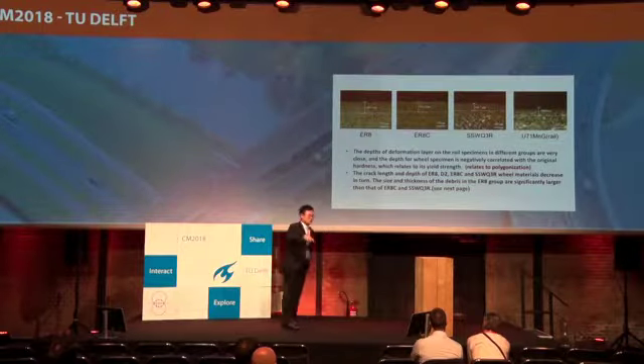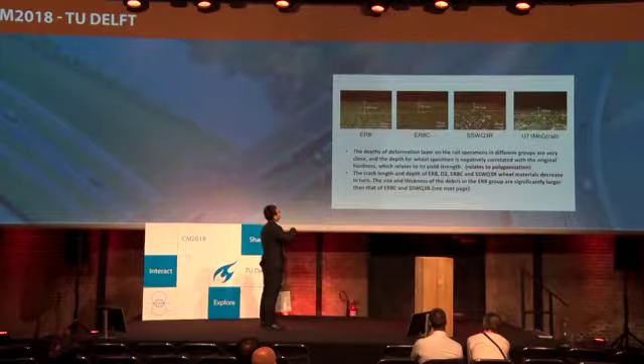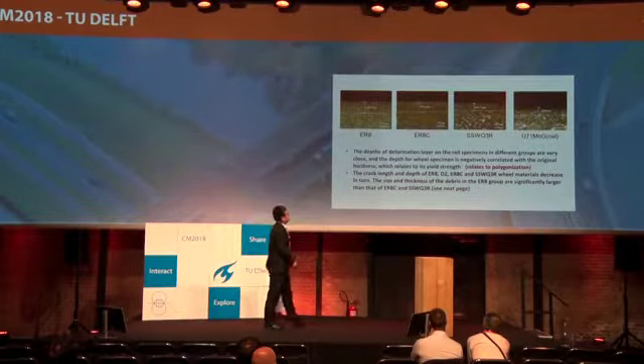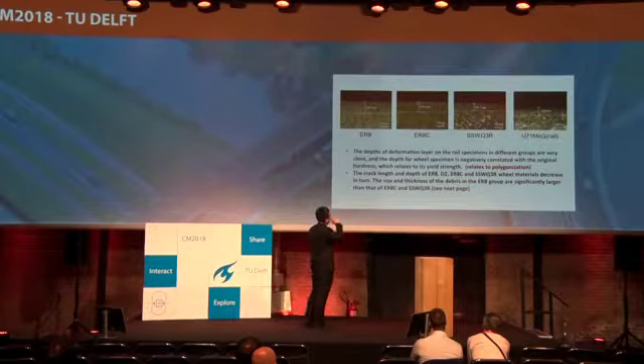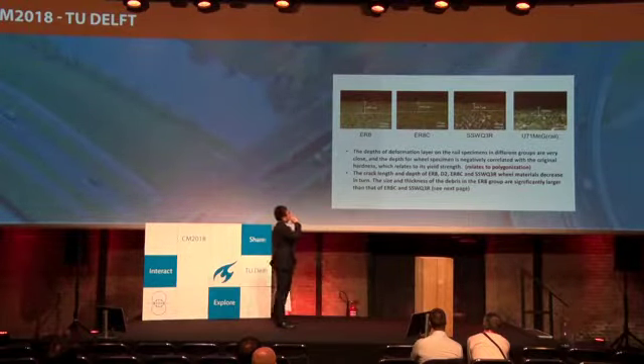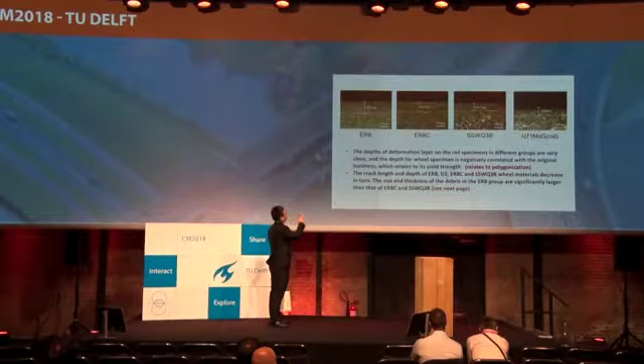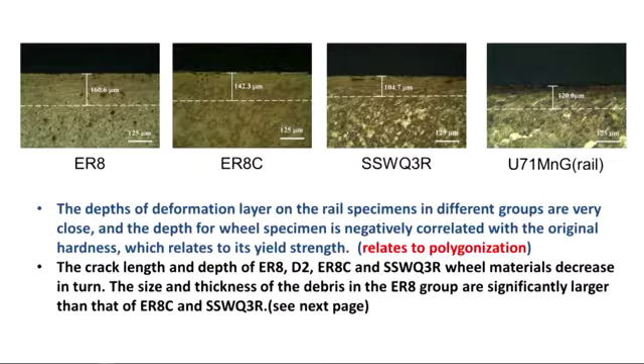And then we sectioned our specimen to see the plastic deformation of the wheel and rail specimen. So we can see that when the hardness of the wheel increases, the depth of the deformation layer on the surface decreases. So it's very simple to understand that as the hardness increases, it needs very high force to make it deformed.